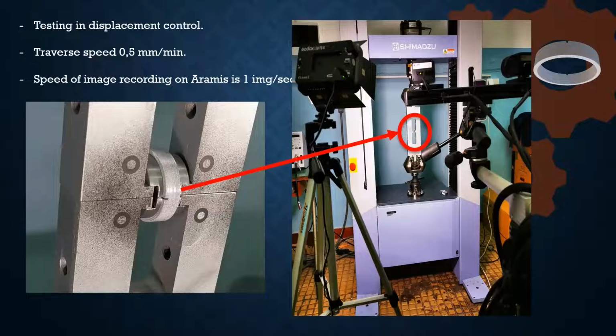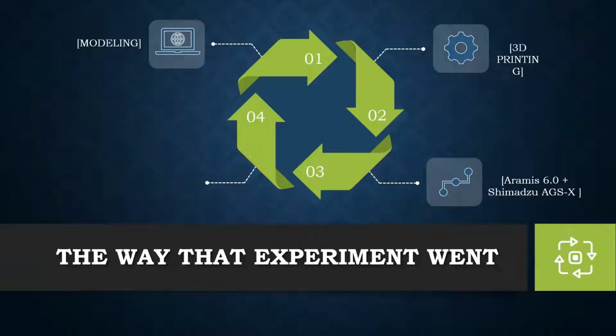In order to harmonize the values of the forces measured on the universal testing machine and the displacements measured by means of Aramis, it was necessary to control the loading of the force from the universal testing machine every 10 stages, or every 10 seconds. And in this way, we determine the harmonization of the release of both systems.